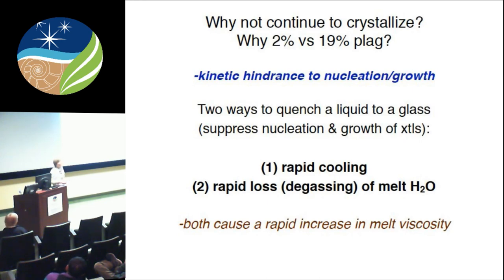So there's two ways you can quench a liquid to a glass. Now, the obvious way is just to cool it really rapidly. And the faster you cool it, the more you'll suppress nucleation and crystal growth. But another way to do that is to lose water. So as you lose water, you increase the viscosity.